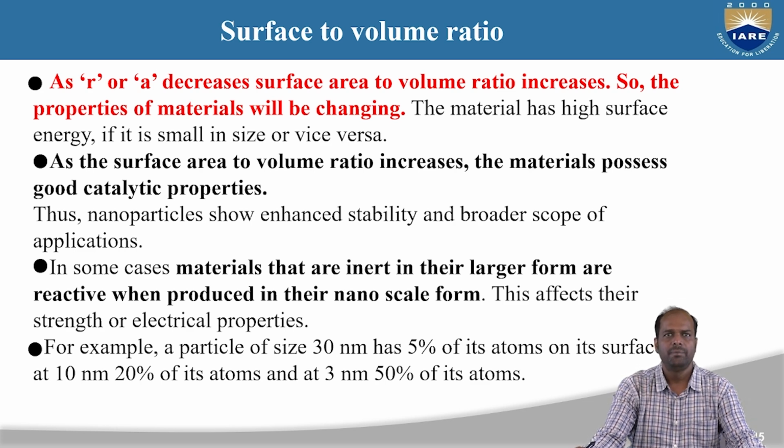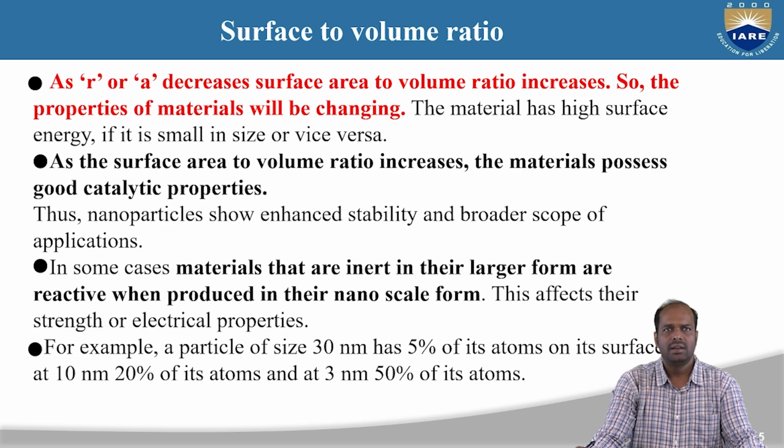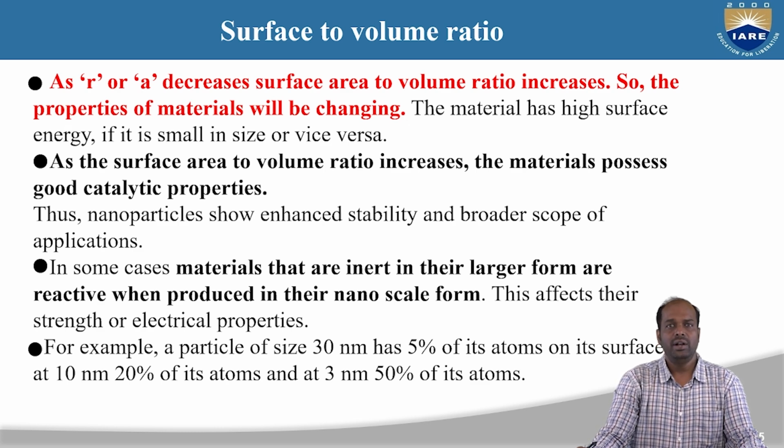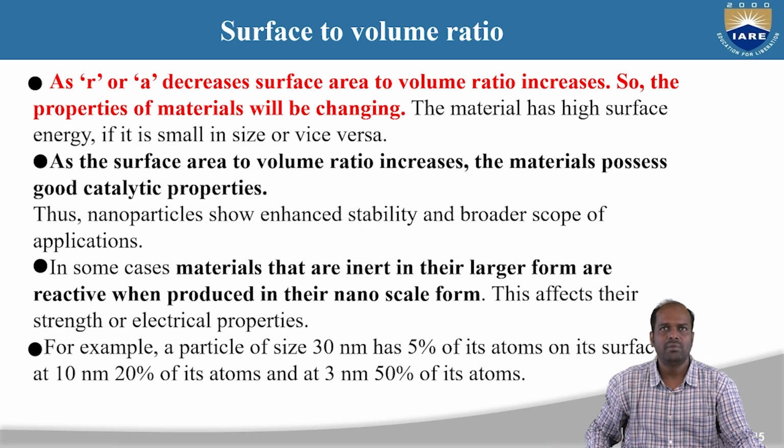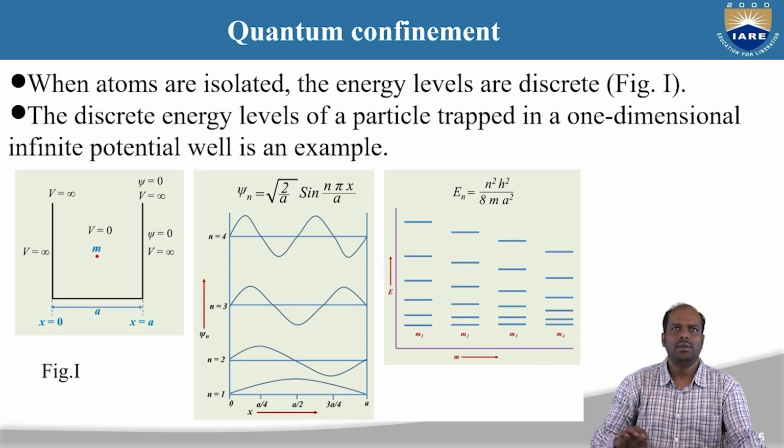For example, at a particle size of 30 nanometers, 5 percent of its atoms are on the surface. At 10 nanometers, 20 percent of its atoms, and at 3 nanometers, 50 percent of its atoms are on the surface. This is the example for surface area to volume ratio.